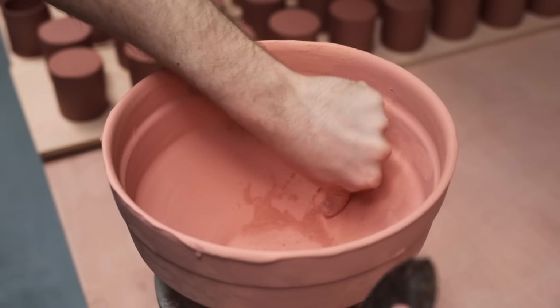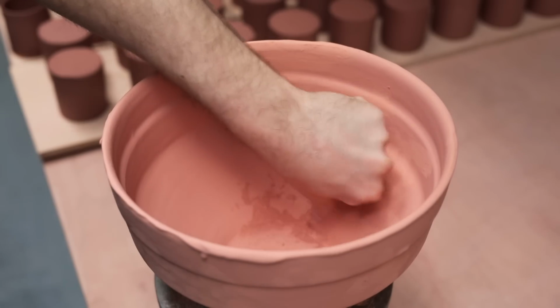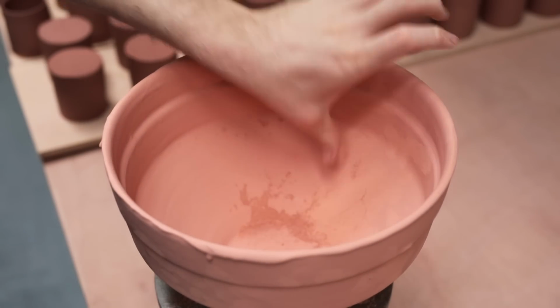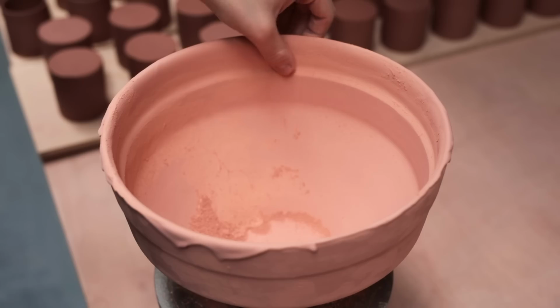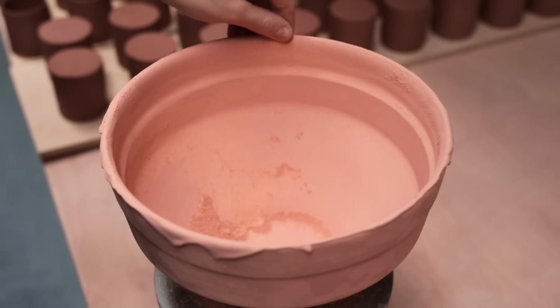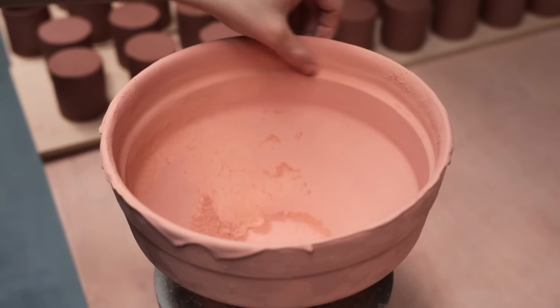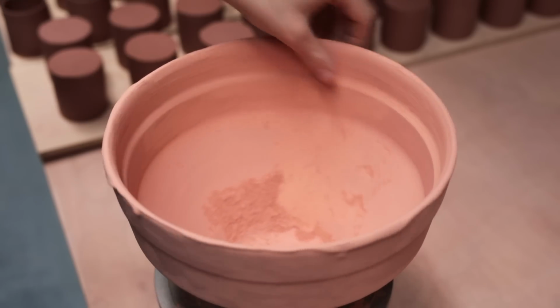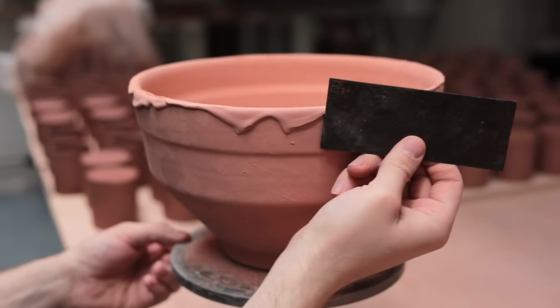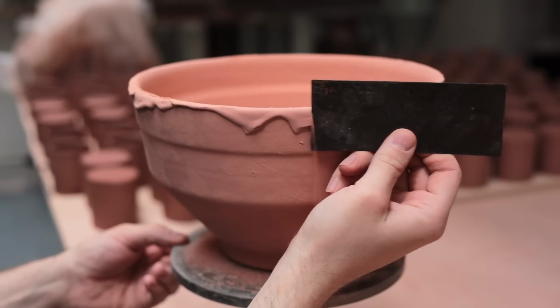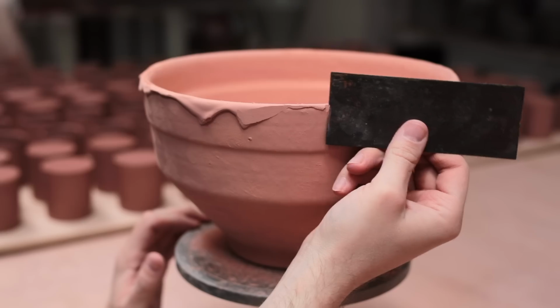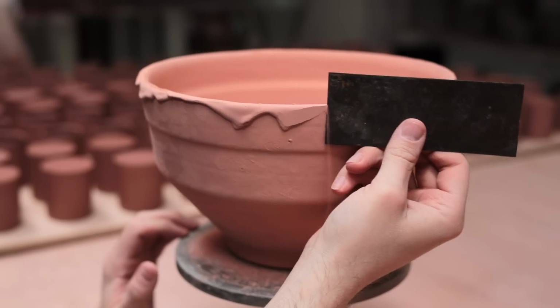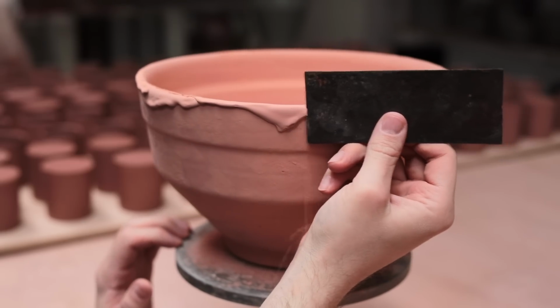This is slow and careful work, as I also don't want to accidentally wipe away the glaze too much, as otherwise I'll be left with a thin spot, which in some cases can look even worse than a thick spot. The really thick parts though have to be removed, as if left, the glaze could crawl on these sections. This is when the glaze begins to separate from itself, leaving small, irregular patches of bare clay.